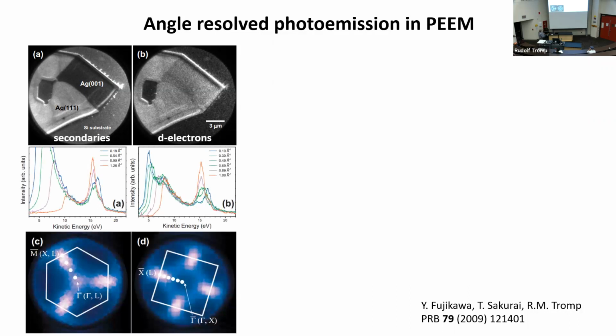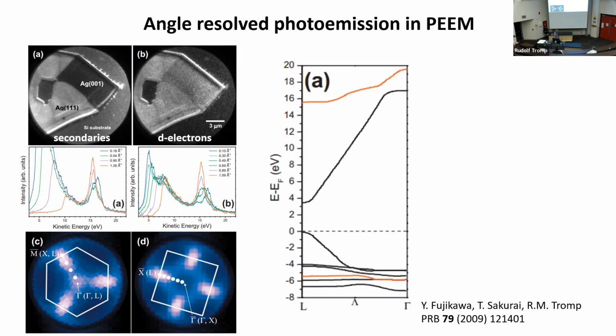Here you see the electron energy spectra. This is excited with the helium-1 light source that's attached to the microscope. So this I don't have to go to a synchrotron for, I can do it at home. And here you see the spectra. And when we take this strong peak that we see, and plot its intensity as a function of parallel momentum on the sample, you see that on 111, there are 3 strong lobes, and on this part of the sample, there are 4 strong lobes, and they're obviously rotated in a different symmetry. Why are these lobes so strong? It turns out that's sort of a coincidence.